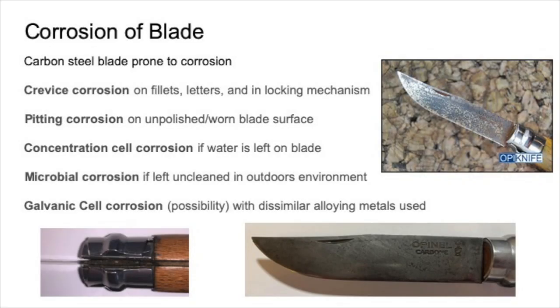One of the primary flaws with this knife blade design is that it's highly susceptible to corrosion. This is especially apparent in high carbon steels, especially those that don't have a high alloying content. The primary mechanism by which corrosion acts is through crevice corrosion. You can see this in the bottom left-hand corner in the locking mechanism, where small gaps create a gradient in concentration, allowing for ion transfer and consequently the formation of rust.